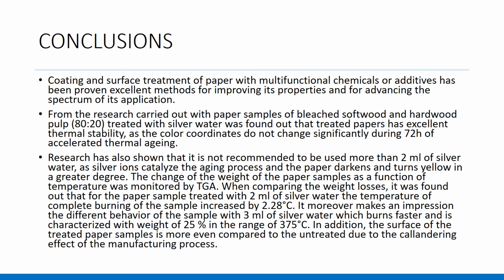From the research conducted, it might be concluded that coating and surface treatment of paper with multifunctional chemicals or additives has been proven excellent methods for improving its properties and for advancing the spectrum of its application. From the research carried out with paper samples of bleached softwood and hardwood pulp treated with silver water, it was found that treated papers have excellent thermostability, as the color coordinates do not change significantly during 72 hours of accelerated thermal aging.